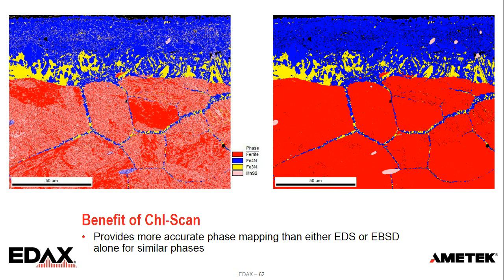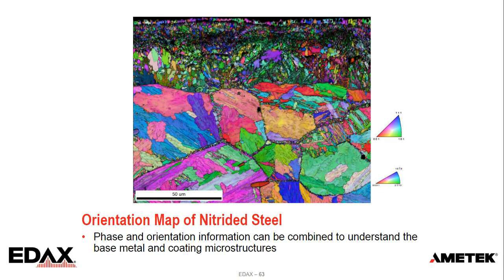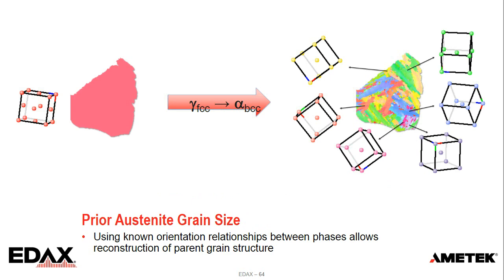And so this just shows the orientations for the different phases. There's different color keys that are used. And for the ferritic grains, these larger ones at the bottom, these are called packets. And this just comes from the transformation from austenite to ferrite, where these patterns in here form a preferred orientation relationship in these packets. And so this is another application question that has been around for EBSD for a long time: measuring the prior austenite grain size.